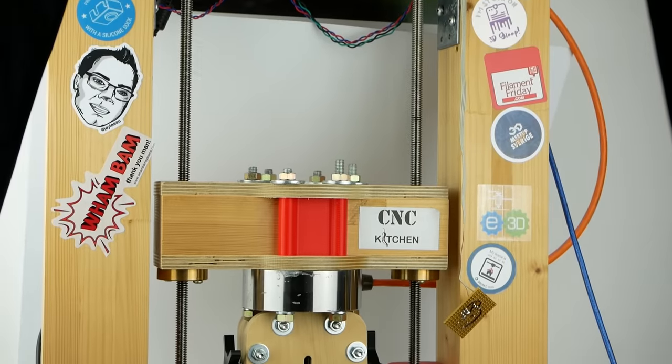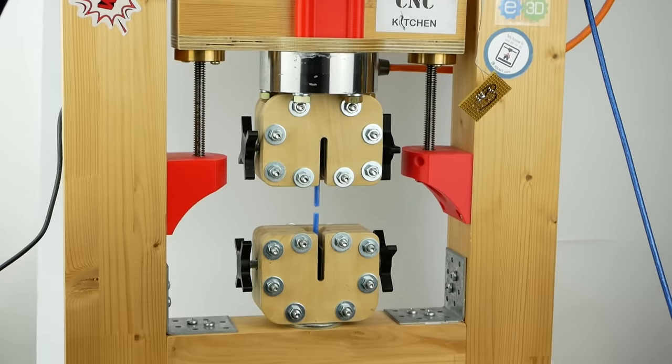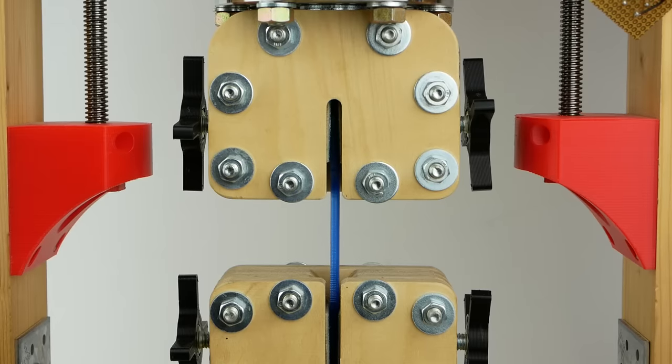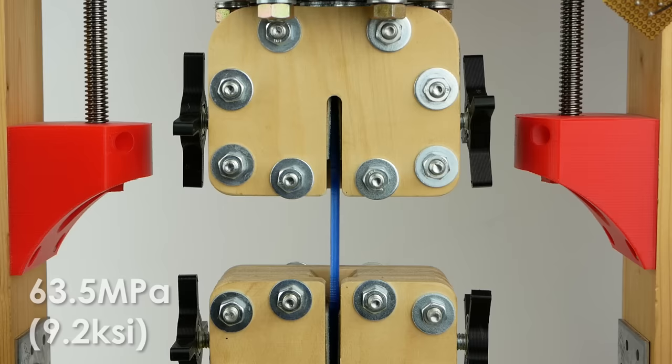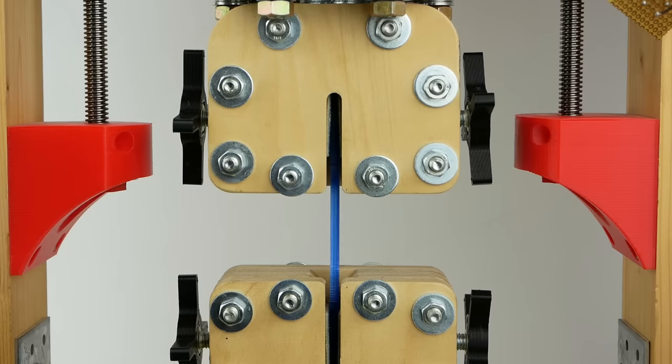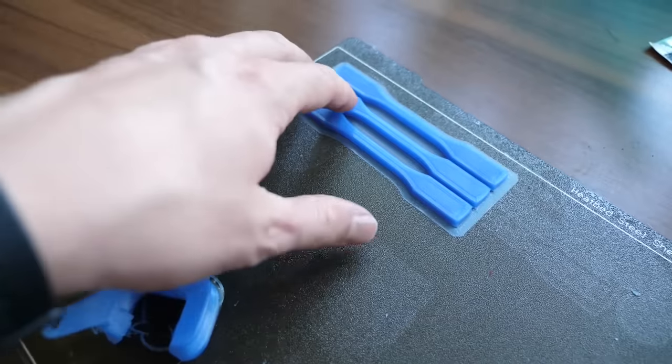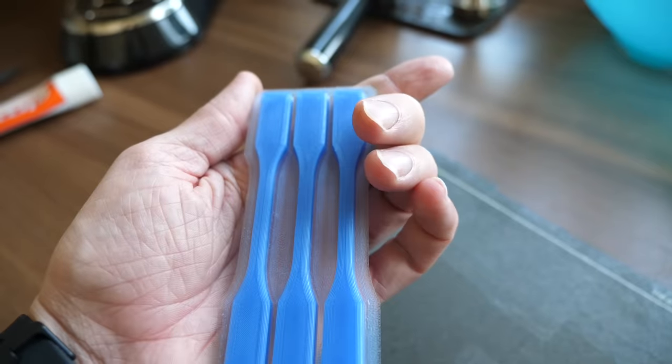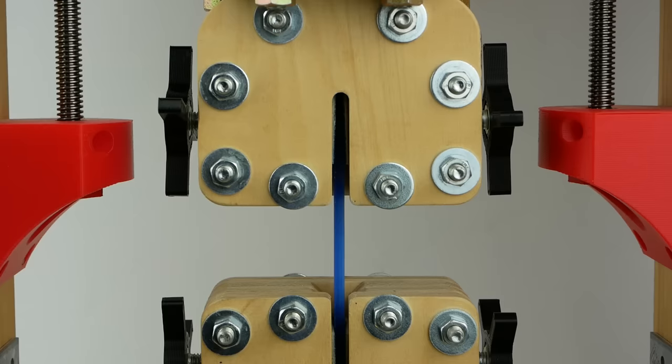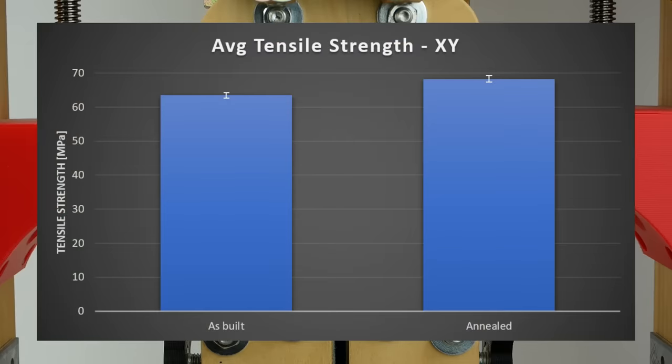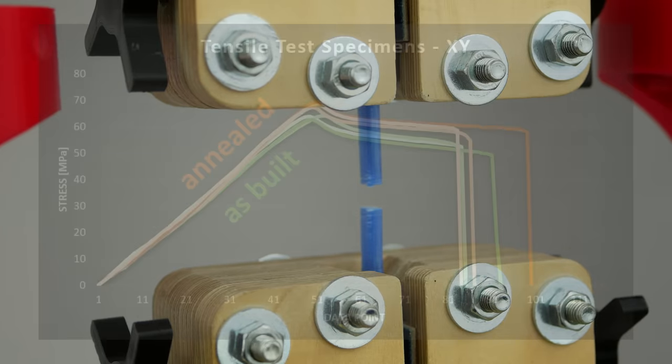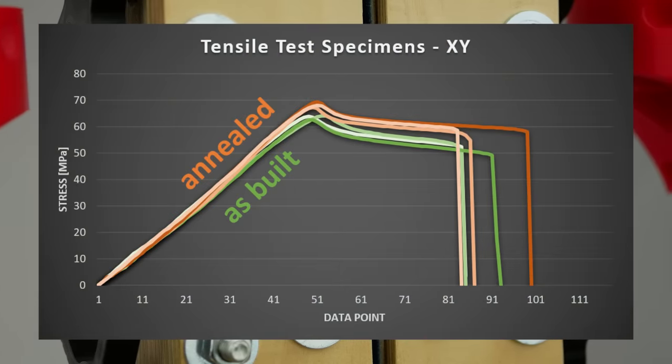Let's first start with the tests performed using my DIY universal test machine. The standard tension test specimens showed an ultimate tensile strength of 63.5 MPa on average. All samples yielded a good bit until they failed. Next I tested the three specimens that I annealed while still attached to the print bed because the other ones were just too distorted. These samples failed on 68.2 MPa on average. This is around 7.5% more than the untreated ones and with a low scatter statistically significant. They also failed quite similarly with a bit of plastic deformation before rupture.